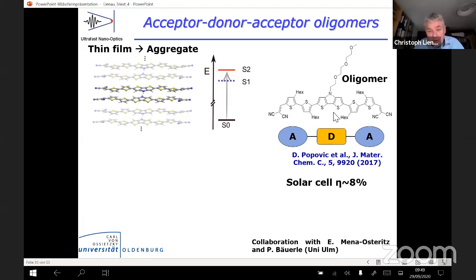In particular, this oligomer here, when you form thin films from it, forms in the form of an aggregate. So basically, the two molecules stack on top of each other, such that they form an H aggregate. If one is pointing in this direction, the other one is pointing in the other direction, sort of as if you have two dipoles that are antiparallelly aligned. So that's the geometry of the system.